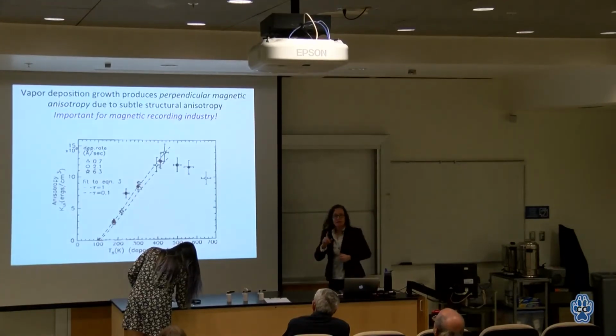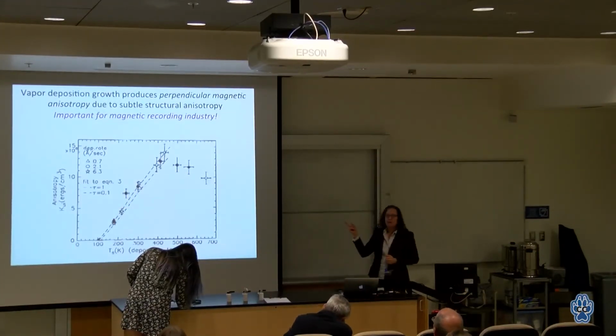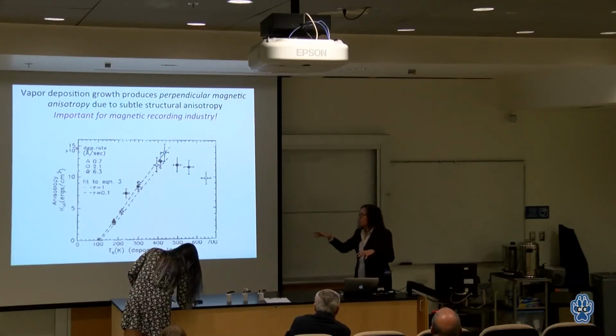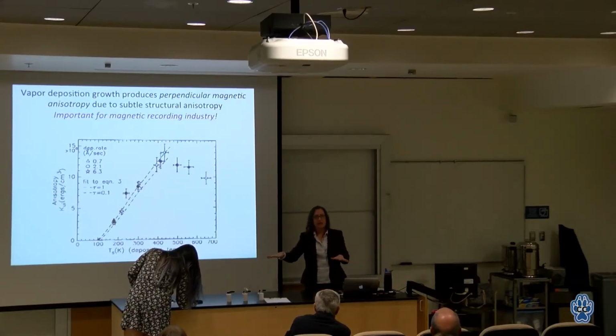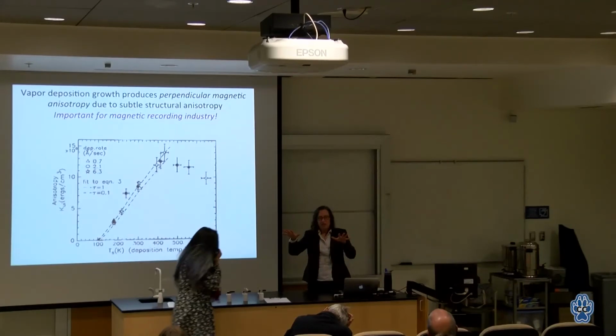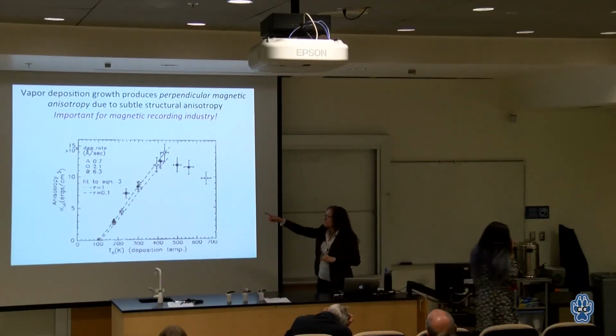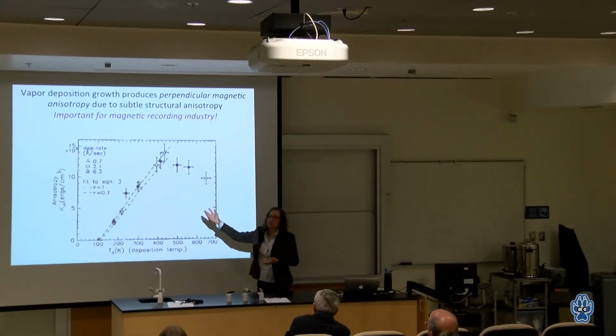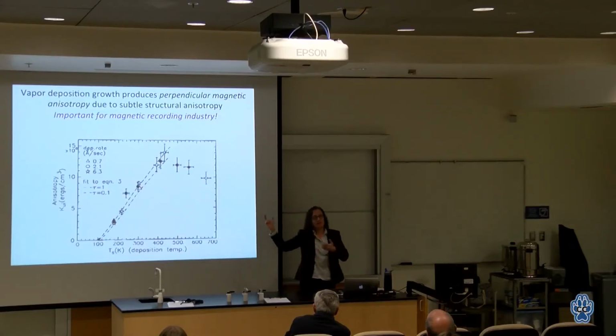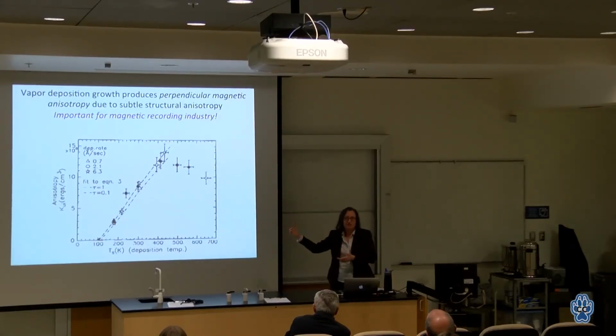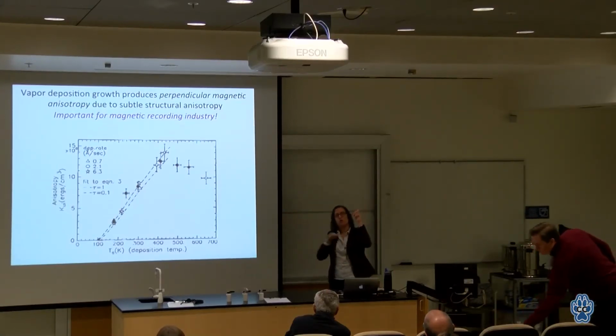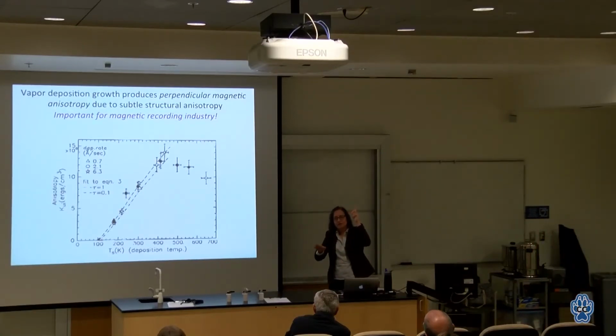So the problem with that argument is the shape anisotropy is competing all the time. Shape always wants to have the magnetism be in the plane. So the thicker I get, if anything, that gets less. So this anisotropy, which is oddly usually called magnetocrystalline anisotropy, despite the fact that it's not crystalline at all, but it is connected to the structure, this anisotropy being out of plane is always competing with the in plane. So all that's going to happen as it gets thicker is the in plane will get less, which will make, if anything, the out of plane even more important.